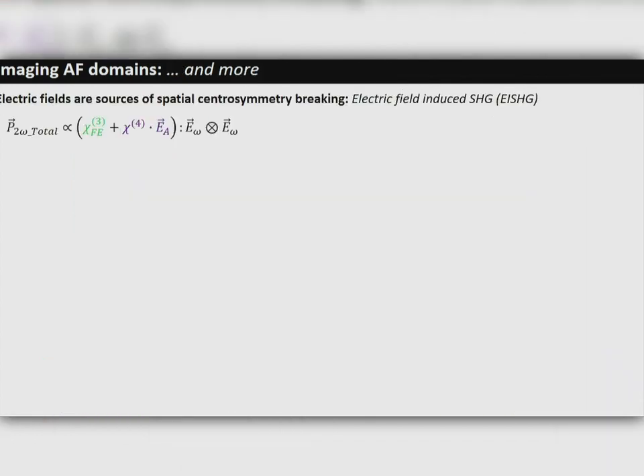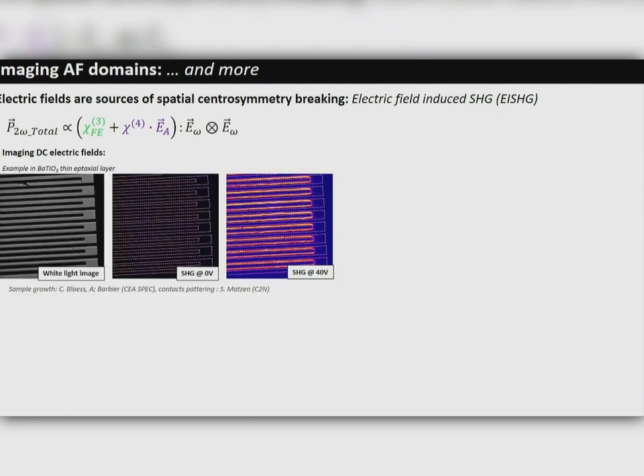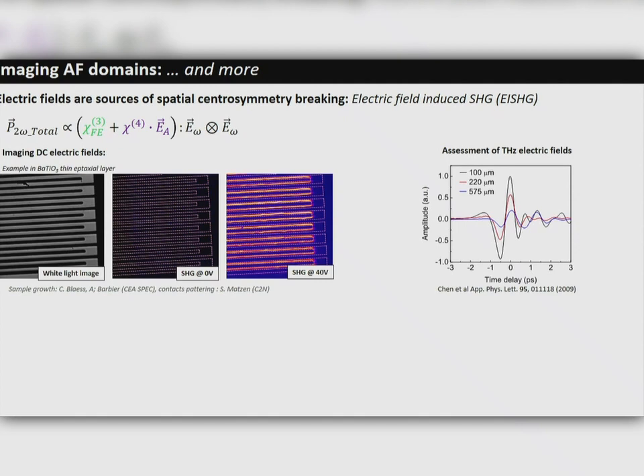But we can do even a bit more, because what we have to note is that electric fields are also breaking the symmetry. And it has been shown, for example, that we can image this electric field. So to illustrate this, this is a little experiment we have done in our lab. So here, these are interdigital fingers on the BTO. We are not expecting to see anything for second harmonic generation. We put a voltage between these fingers. So at 0 voltage, we see nothing. And at 40 voltage, suddenly you see some second harmonic generation appearing. This is basically the contribution of what we call the electric field-induced second harmonic generation. People have even done that to measure terahertz field. So it's a very nice technique.